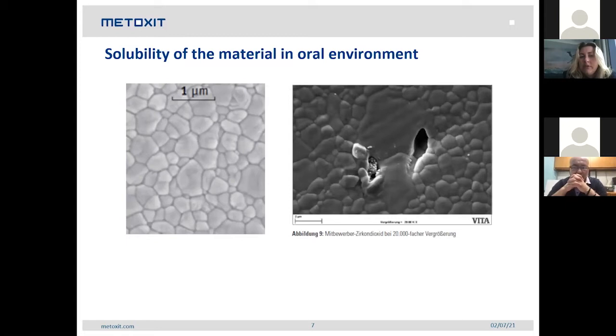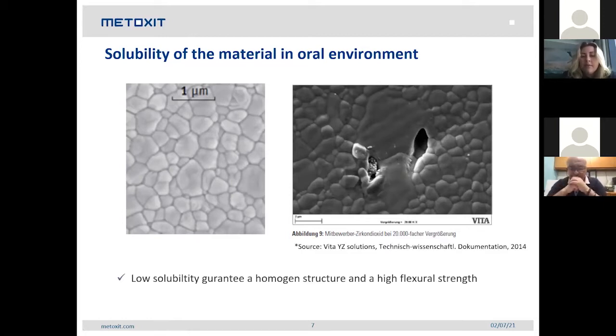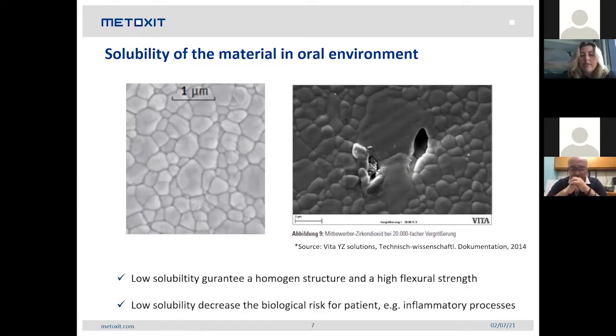Sometimes, if you don't take care of your raw material, it can look like this. After some years, you have some cracks, some gaps. And this, you can imagine, is not good for the flexural strength when you have a gap in your structure. And some of these particles can increase the biological risk for patients. So you need a low solubility to decrease the biological risk, because if you have some of these particles in the body, it can also cause inflammatory processes.